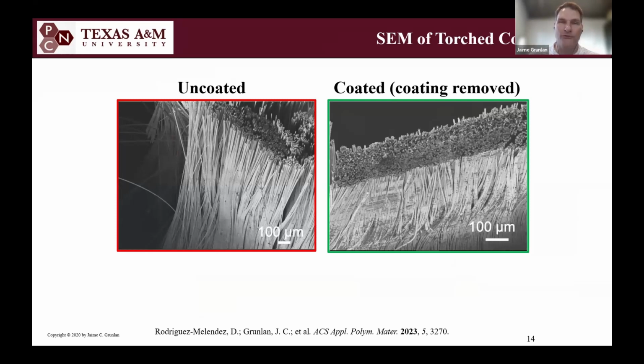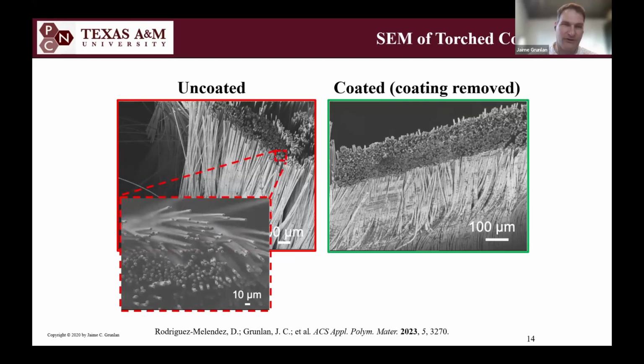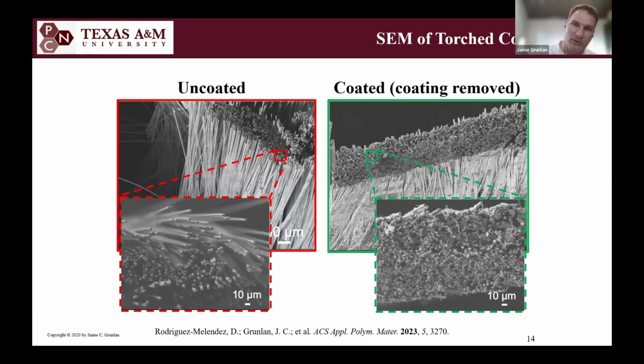And you can see it in the uncoated. These are post-burning SEM images, and so you can see the uncoated composite. You can imagine most of the epoxy is fully gone, and you can see the fibers are all splayed out. And if we zoom in, you can tell that they're not sticking together anymore. But the bulk of the composite that was coated with this sometimes 4 micron, we went up to 15, 20 microns of coating. But in any event, this quite thick,